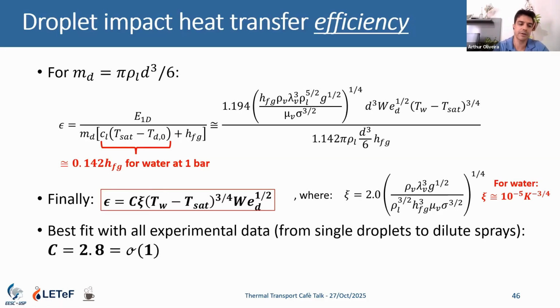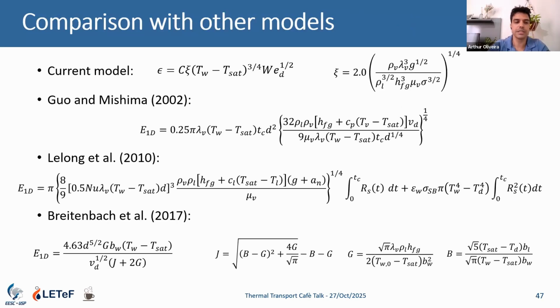Considering the data we collected, the fit parameter is 2.8. So we were happy to see this parameter, because it's in the order of 1, meaning the scaling law we used is not too far from reality. If we had found, for example, a fit coefficient of 1,000, we'd know something was not right, but it's close to 1, so those are good. That's good news. So what we did is compare that to other models from the literature.